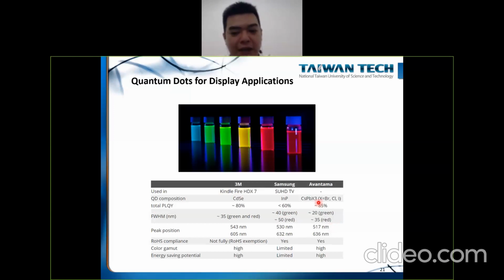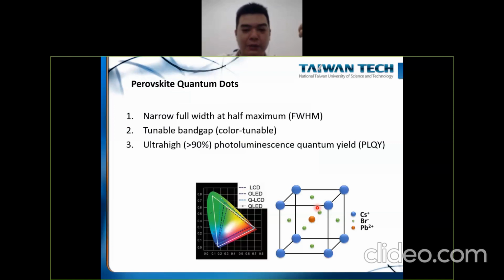And you can see that the quantum yield is good and the emission width is good for this material. Even though it has lead, the restriction on lead is not as strict as for cadmium, so lead can still be used for electronic devices. But the most important problem for this type of material is that it's unstable. It's quite unstable. And this slide just shows the properties of perovskite quantum dots.